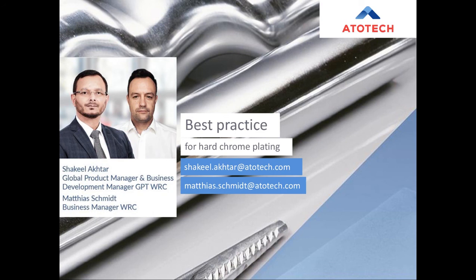The difference is actually the catalyst system, and the processes from HEAF 25 over KR to HMC represent the increase in the demand for higher corrosion resistance over the last years. So basically, a higher corrosion resistance and higher microcrack count was required. Therefore, the original HEAF 25 process was improved with different catalyst systems in order to provide a higher number of microcracks. So the HEAF 25 will provide the lowest, KR the middle, and the HMC will provide the highest number of microcracks.